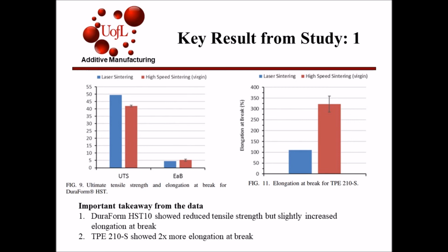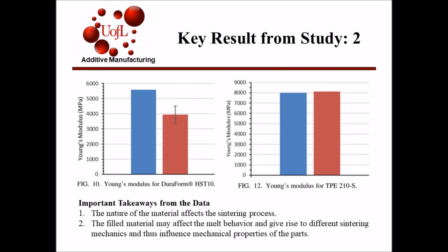The TPE 210S material showed more than 2 times elongation at break for the high-speed sintering method when compared to the laser sintering method. For the Young's modulus, the laser sintering method shown in blue produced a higher value than that of the high-speed sintering for the Duraform HST10 material. It was believed from the report that the nature of the material can affect the sintering process. Since Duraform HST10 is a filled material, it is believed that this may have affected the melt behavior and influenced the mechanical properties of the parts. For the TPE 210S, the difference in the Young's modulus for either process is negligible.